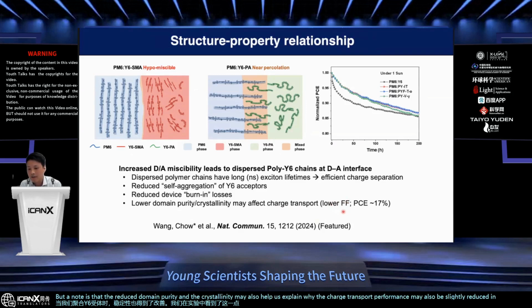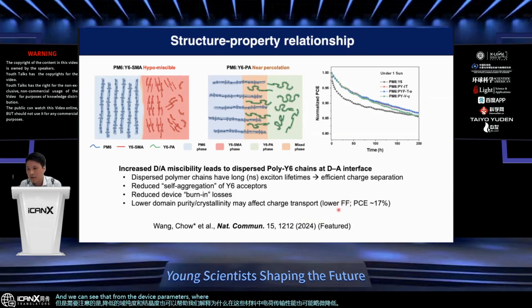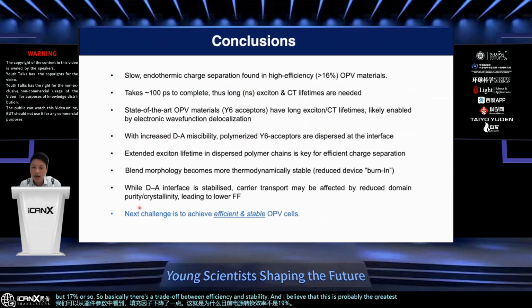And we can see that from the device parameters, where the fill factor is dropped a little bit, and that's why the power conversion efficiency is not 19% at the moment, but 17% or so. So basically there's a trade-off between efficiency and stability. And I believe that this is probably the greatest challenge that we face right now in organic PV research.